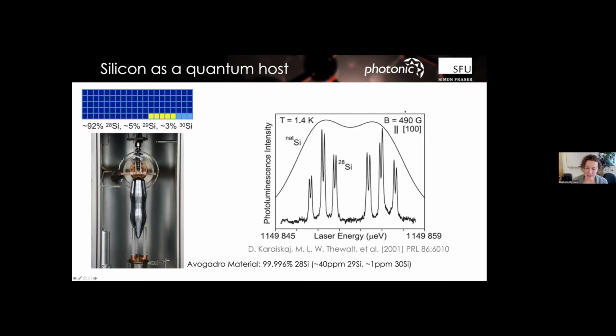is indicative. So the defect on the previous stage of this slide that had 3-hour coherence times, that's a phosphorus defect in silicon. So it's a very standard defect in silicon. And it has optical transitions. They're not quite in the telecom regime. This is near 1 micron. And they have optical transitions that are excellent in terms of their line widths,